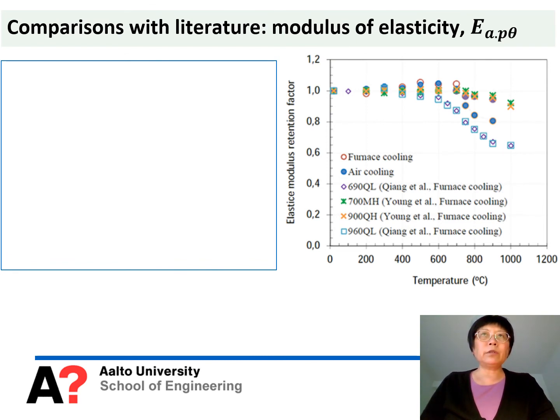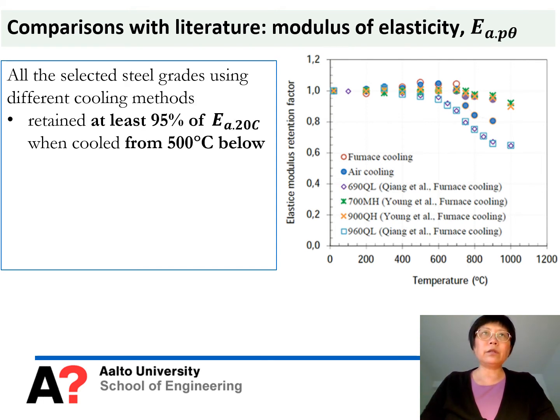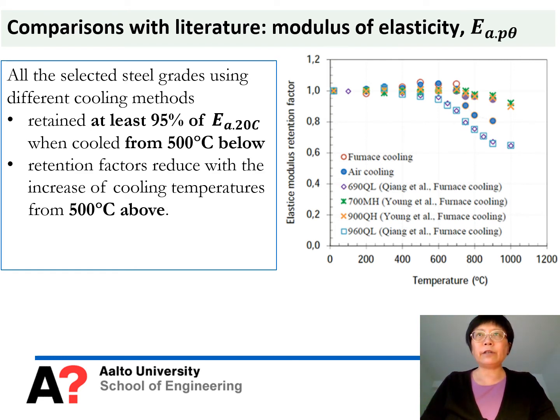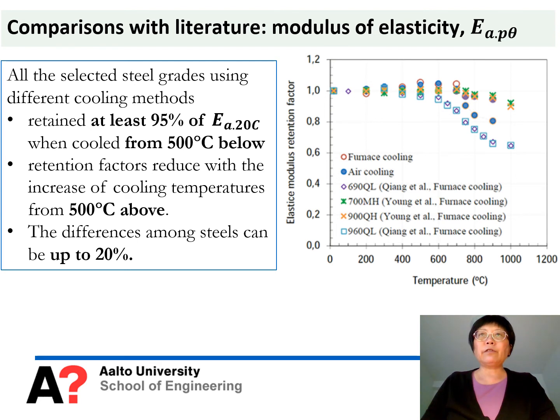So when the modulus of elasticity is compared between this study and literature studies, it can be seen that from 500 degrees, all the selected steel grades retained at least 95% of the modulus of elasticity, but from there, the retention factor reduced linearly with the increase of cooling temperature, and the difference among different steel grades can be up to 20%.